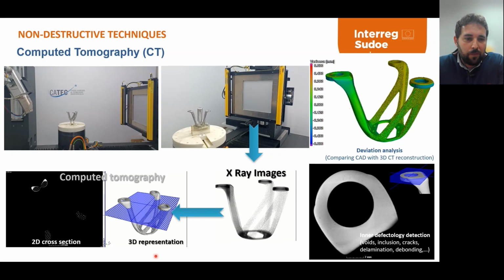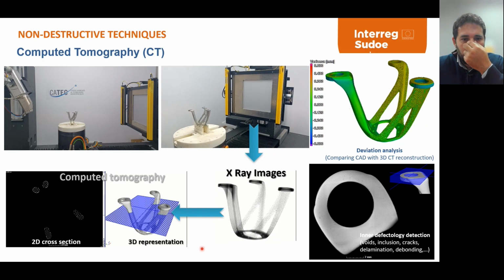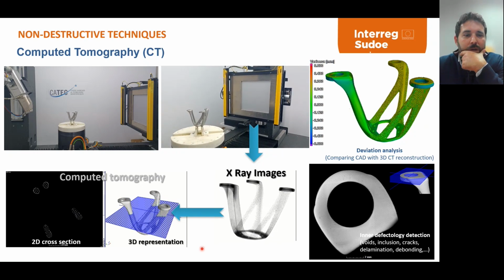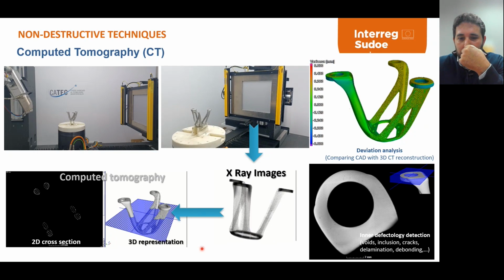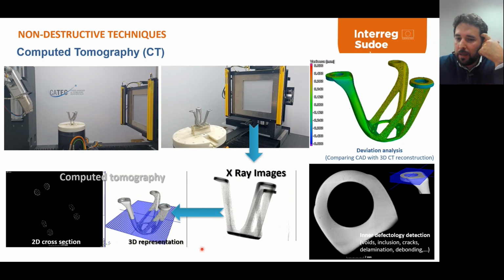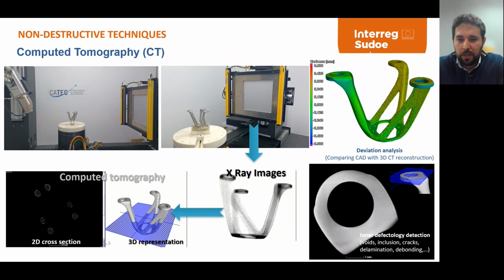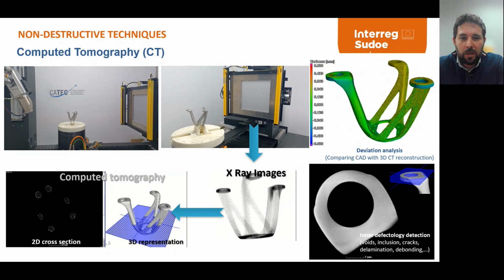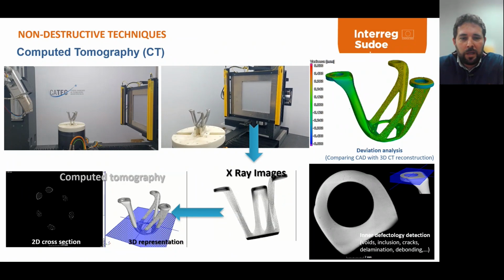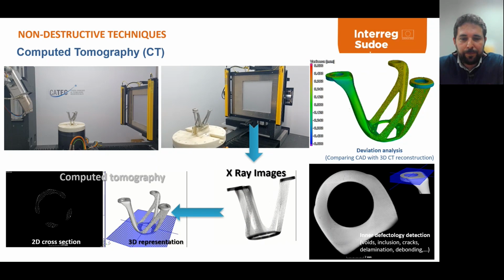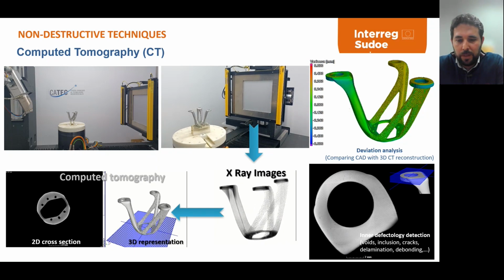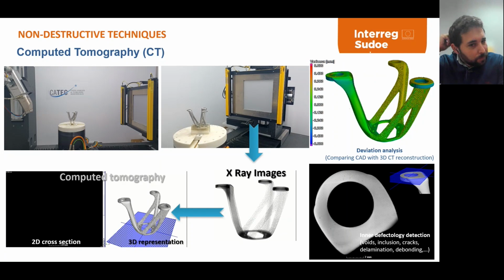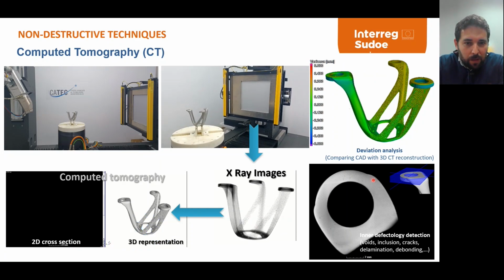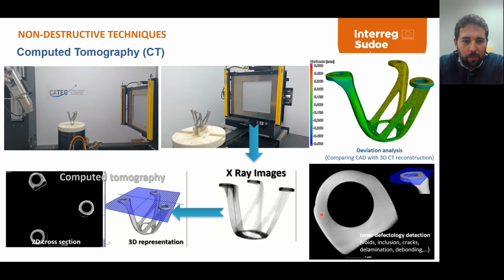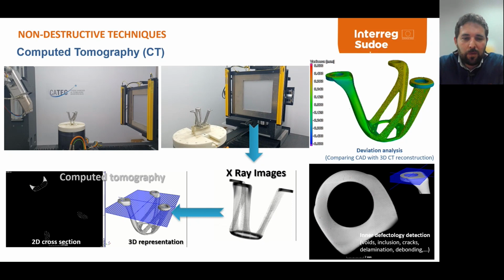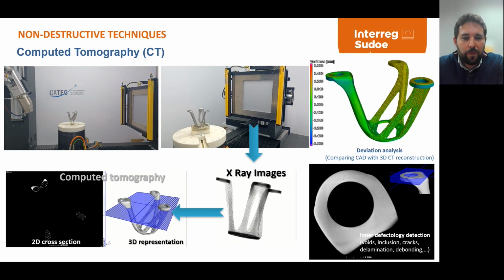So you are able to see all the inner and outer features. This technique generates a 3D representation of the inspected component. So it's also used for dimensional analysis, even for really complex geometries. As you can see, this lattice structure in here, and inner features, inner cavities. This technique is very powerful detecting inner defects. As you can see here, maybe, I don't know if you can see some pores, some voids. It is also powerful to detect inclusions, cracks, etc.